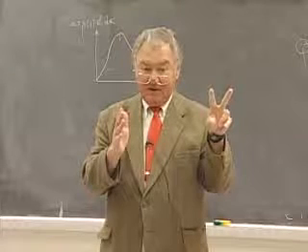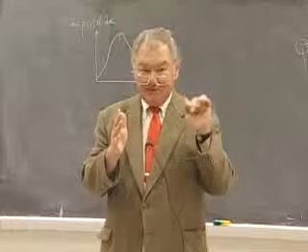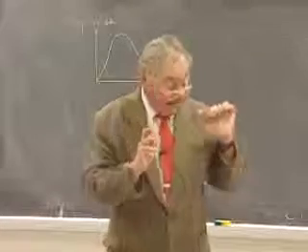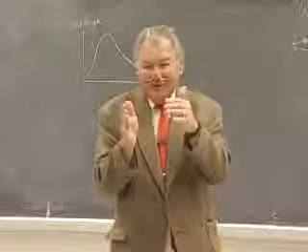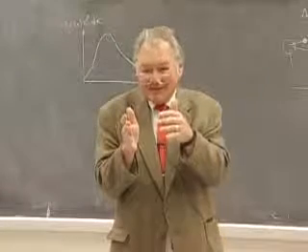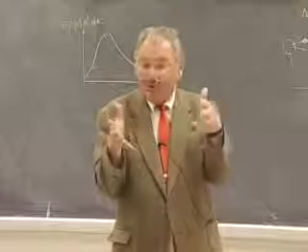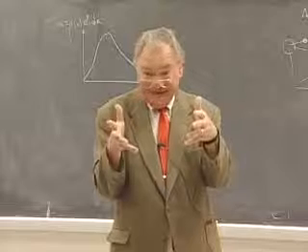What he had done was look up the radius of silver in Pauling's tables, and he didn't realize that all of Pauling's original radii were normalized to octahedral 6-fold coordination, which makes the radius larger. That's why the silvers didn't fit in any of the interstices.